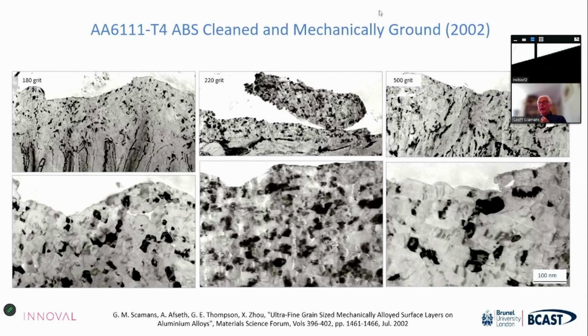Quickly after looking at rolled aluminium surfaces, we looked at a 6000 series surface, and we looked at what happened when it was mechanically ground. You can see that whatever grit size you use for mechanically grinding, you actually get pretty well the same result. The coarser the grit, the deeper the deformed surface layer, but generally the grain structure, the ultrafine grains formed by grinding, are probably nicer than the ones formed by rolling because they have less oxide with them, and you can really see the beauty of the ultrafine grains. And all of these have a profound effect on the performance of the materials.